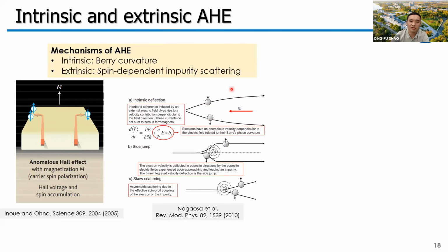These mechanisms will generate a transverse velocity for the electrons. According to this simple picture, where these arrows are the spins of the electrons, we can clearly see that electrons with opposite spins get the opposite transverse velocity. So if we have only a spin neutral current, where the numbers of spin up and spin down electrons are the same, we will not have a net transverse velocity to generate a finite anomalous Hall effect. Only if we have a longitudinal spin polarized current, where the numbers of spin up and spin down electrons are not equal, can we have a net transverse velocity for a finite anomalous Hall current.